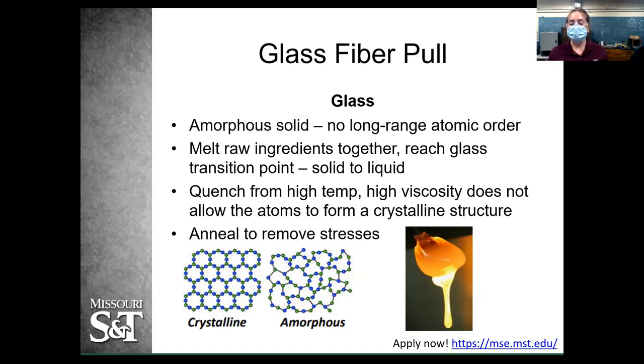The way we make glass is we take all the raw ingredients, bring them up to a really high temperature until they melt into a liquid, and then we quench it really fast — taking it from a very high temperature down to a very low temperature quickly. That quenching does not allow atoms to form a crystalline shape, causing them to freeze wherever they are. It's like immediately freezing ocean waves versus slowly cooling them down to a flat surface. Because we quench, that leaves residual stresses in the glass, so we have to do a process called annealing to remove those stresses.